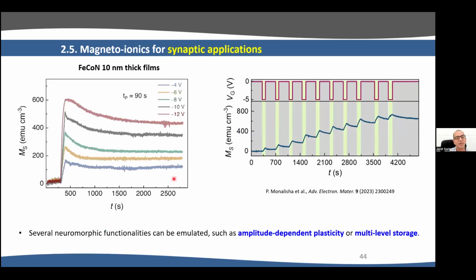For example, here we have iron cobalt nitride, 10 nanometer thick. Here the material again is paramagnetic, and we activated the ferromagnetic properties using different voltages, applied for 1.5 minutes.